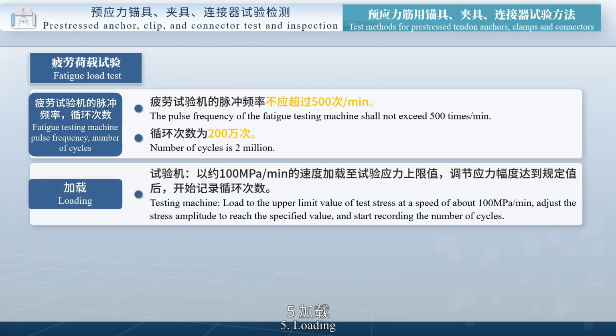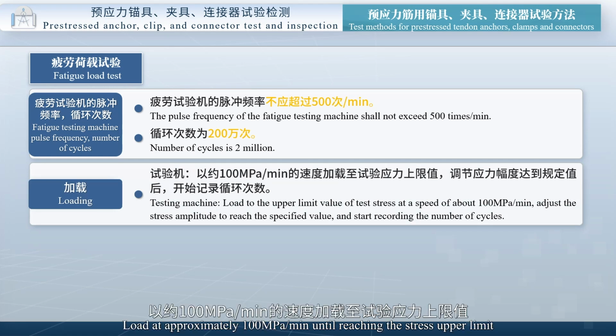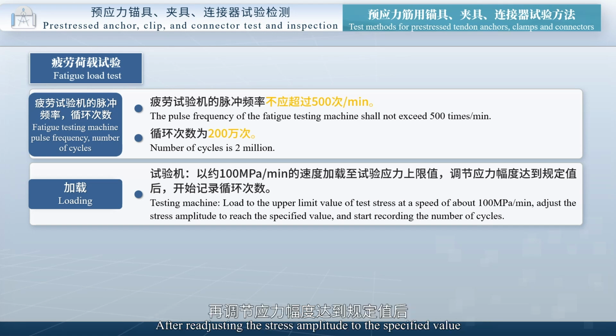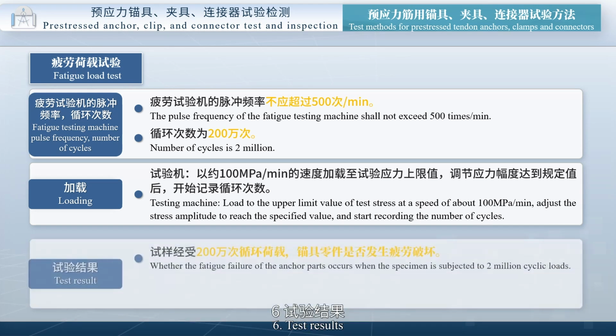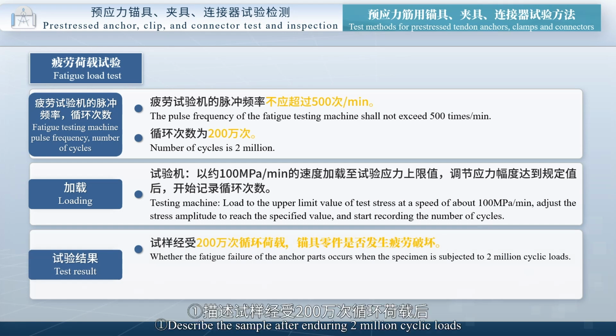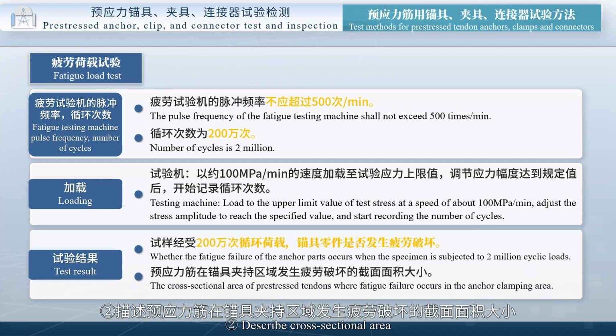Fifth, loading. According to the testing machine used, load at approximately 100 megapascals/min until reaching the stress upper limit. After readjusting the stress amplitude to the specified value, begin recording the cycle count. Sixth, test results. First, describe the sample after enduring 2 million cyclic loads: whether fatigue failure occurs in anchor components, and describe the cross-sectional area where the pre-stressed tendon experiences fatigue failure in the anchor clamping zone.